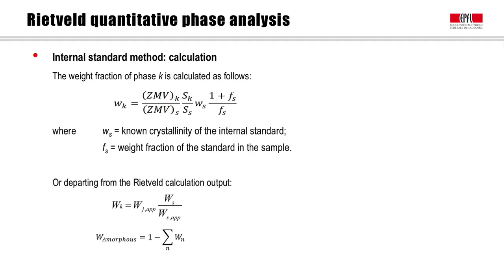A second case is that the apparent weight fraction equals the weighed amount, for example 20% for 20%, indicating no or very little amorphous or unidentified material. The third case is that a lower amount of standard is quantified than what was weighed, which indicates some problem in the experiment or data analysis. The total weight fraction of all amorphous and/or unidentified components can be calculated as the difference between the sum of all crystalline components and 1, i.e., the difference from 100% gives the amorphous phase fraction.